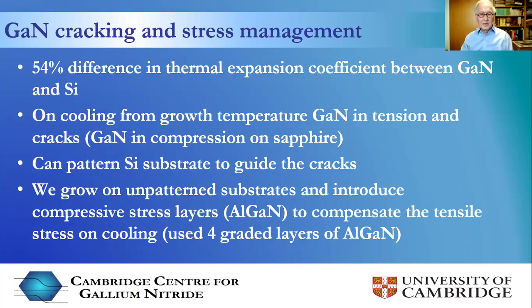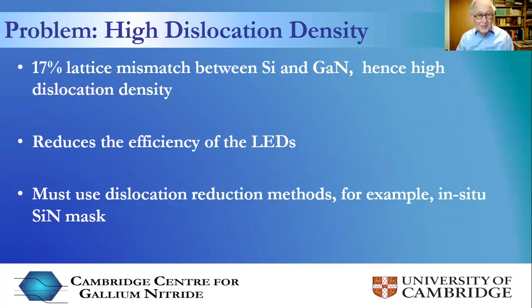And what we found was - this is stress management - we introduced 4 graded layers of aluminium gallium nitride. So there's a lot of trial and error here to see what worked. But this huge compressive stress that you were introducing this way, you can exactly compensate the tensile stress. Say it the other way: you introduce compressive stress to exactly compensate this tensile stress, so the wafer doesn't crack and remains flat.